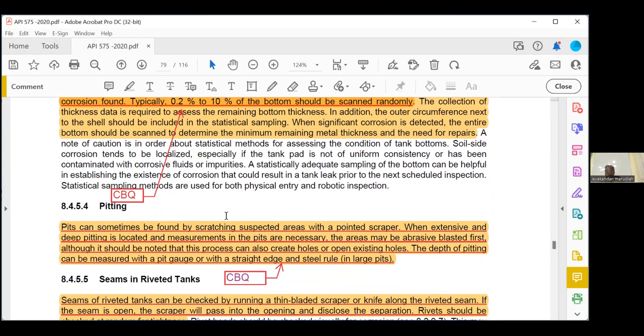Then pitting. So how will we measure the pitting? Again, MFL. Suppose you have access to the pitting, top side pitting, you can measure the depth of the pitting by using a pit gauge. Then highlight this one. Pits can sometimes be found by scratching the suspected areas with a pointed scraper. When extensive and deep pitting is located and measurement of the pits is necessary, the areas may be abrasive blasted first, although it should be noted this process can also create holes or open existing holes. Then the last line is important.